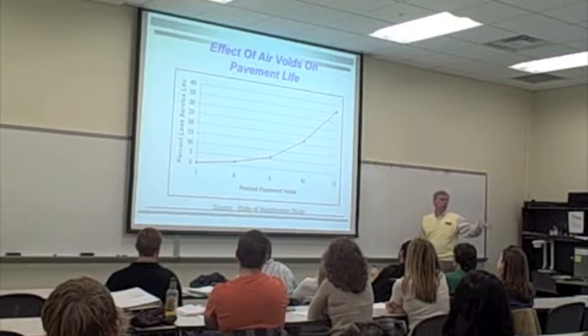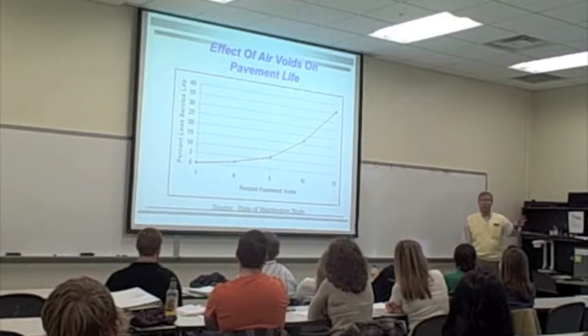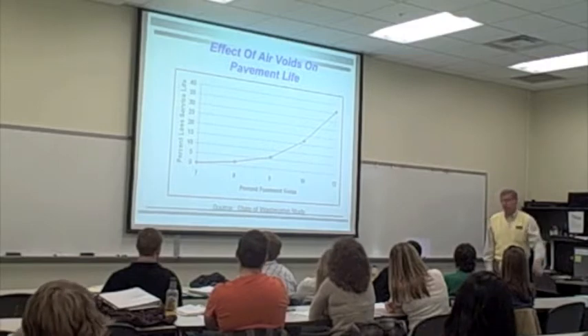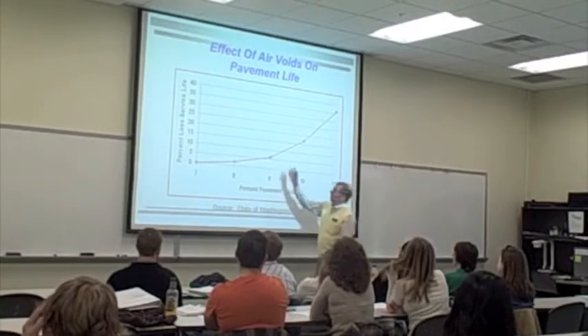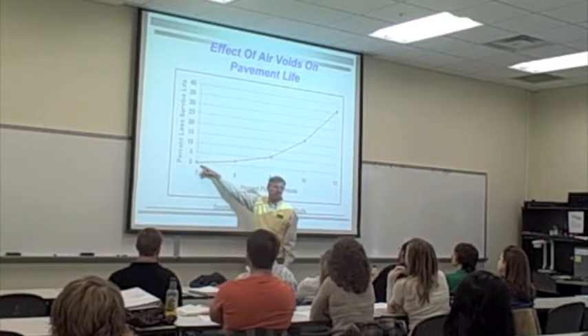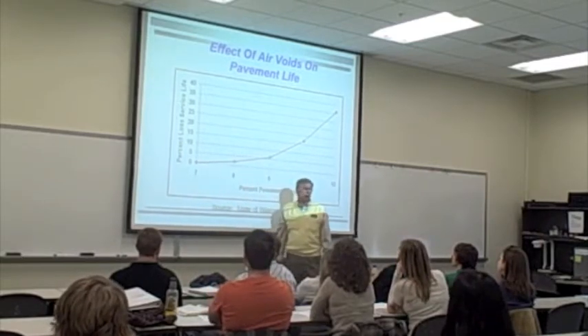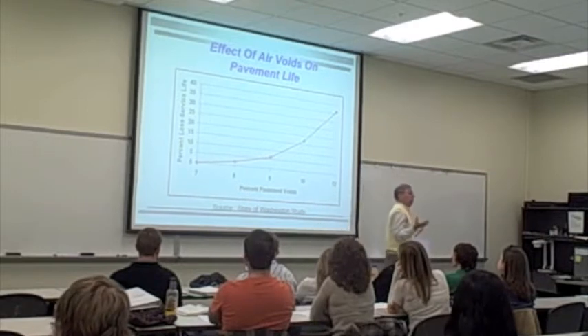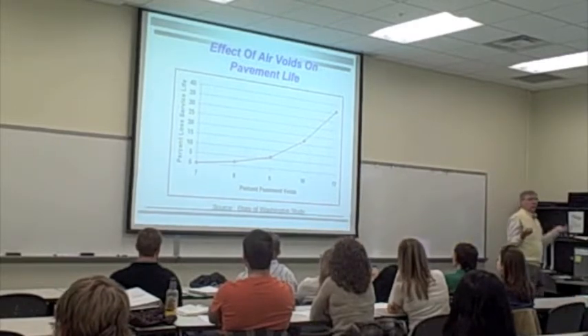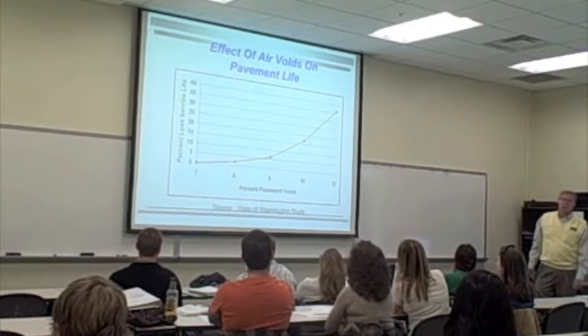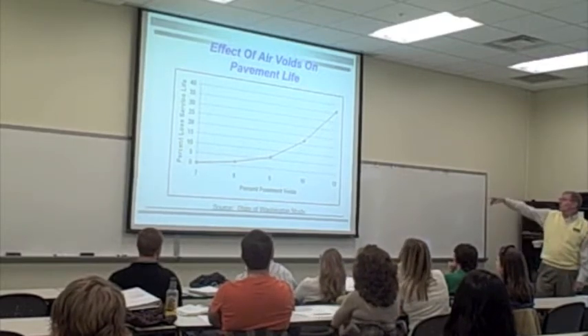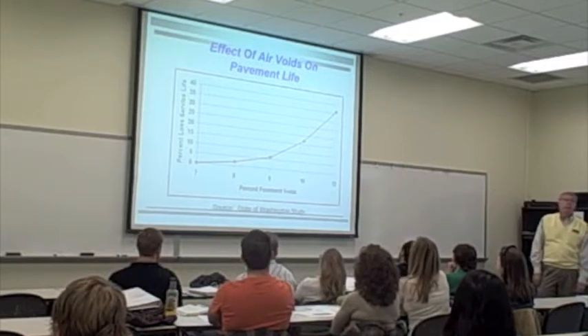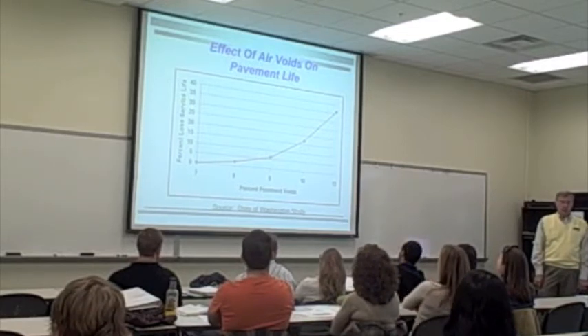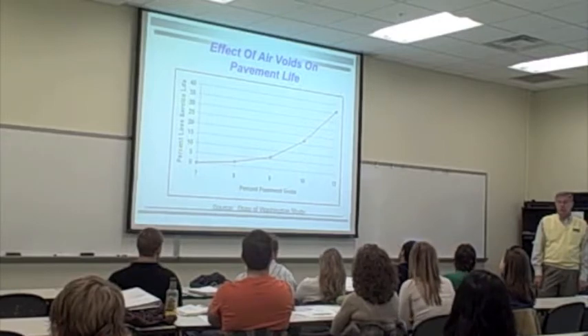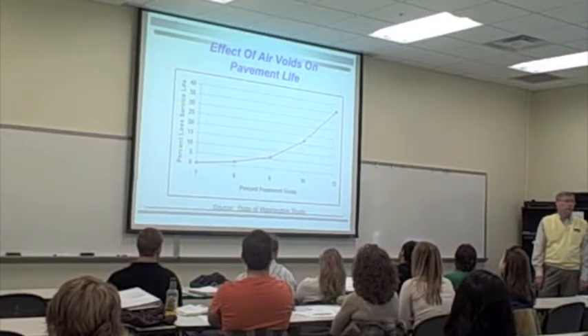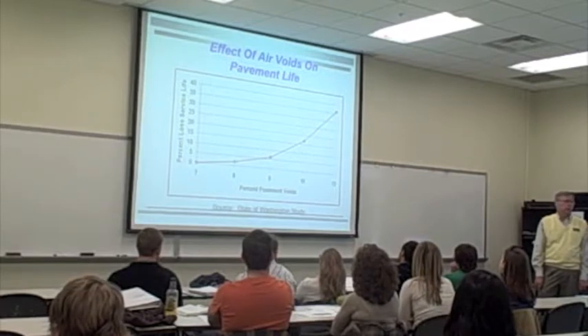What happens if you don't smack it to where you wind up with more than 8% air voids? A study in Washington, they had pavements that they constructed really tight, and then they had other pavements that weren't that tight, and they evaluated how much life we lost. Get to 9% air voids, you lose about 6% of your pavement life. Get to 10% air voids, you're losing, what is that, 17, 18% of your pavement life. You design a pavement for the last 12 years, it's now down to about 10 years. Big deal? 20% of your pavement value.